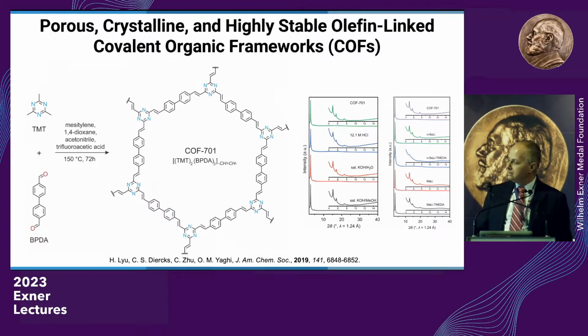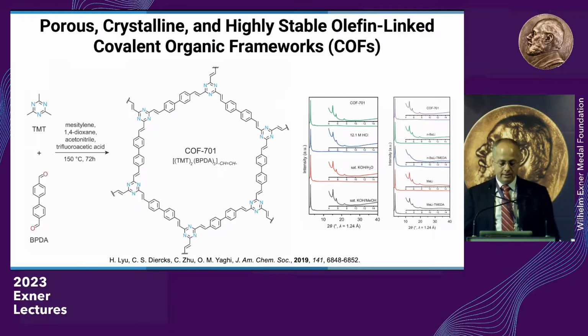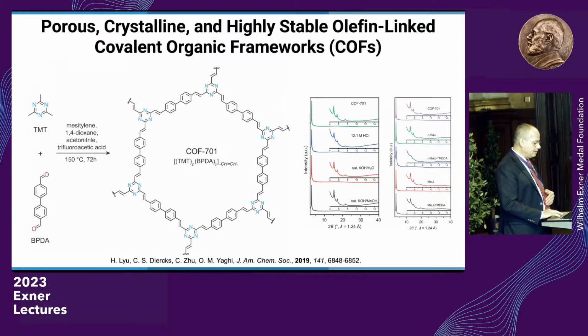And many years ago, I and many others thought you cannot crystallize structures of this kind. These are extended, in this particular case, 2D structure, made entirely from carbon-carbon bonds and carbon-nitrogen double bonds. And therefore, the backbone is extremely robust. Okay, this changes organic chemistry from molecular chemistry into extended structures. And you can see the powder diffraction shows that the structure, the COF, is stable, even in concentrated acid, base, and corrosive media.